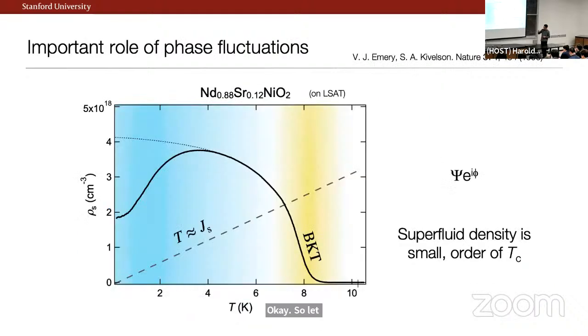So let me just tell you where we are in order to try to get some advice from some of the experts here. This is actual data, but just a cartoon of representative data. Again, we're following this improvement in the material science, and now we think we can do some much higher precision or accurate measurements. This is how it looks. This is a measure of that superfluid density as a function of temperature. Again, we have this very funny low temperature feature associated with, we think, 4f moment ordering on the neodymium site.